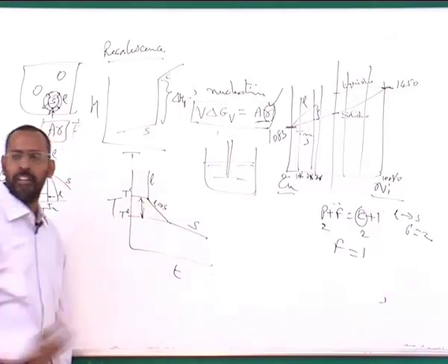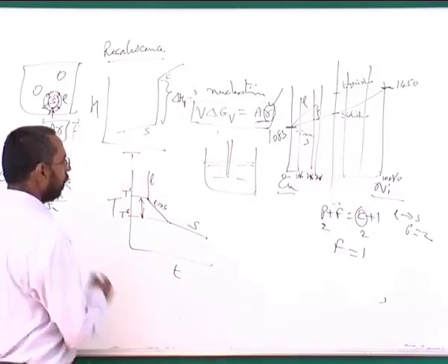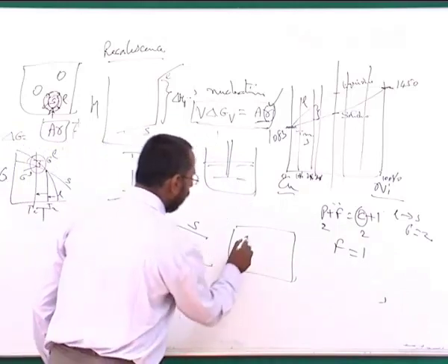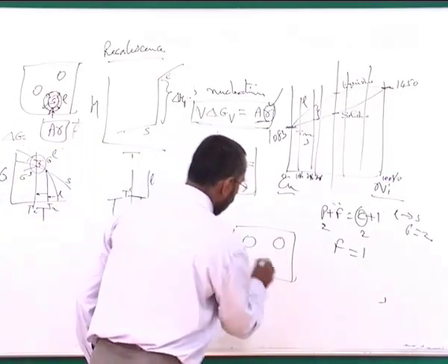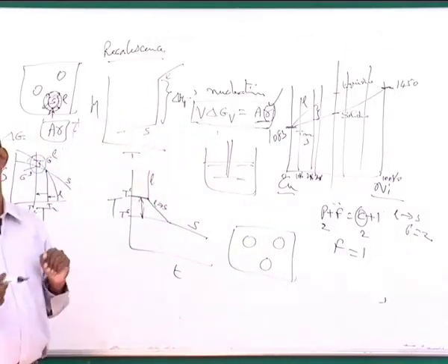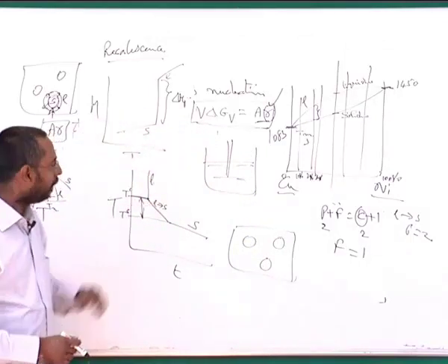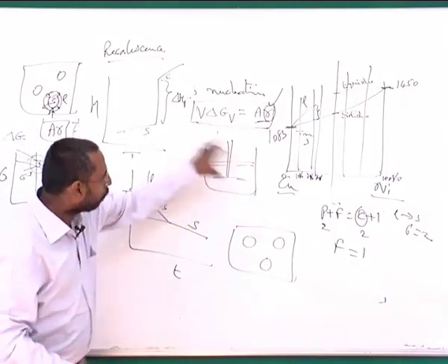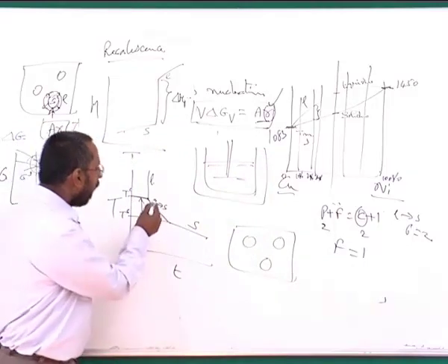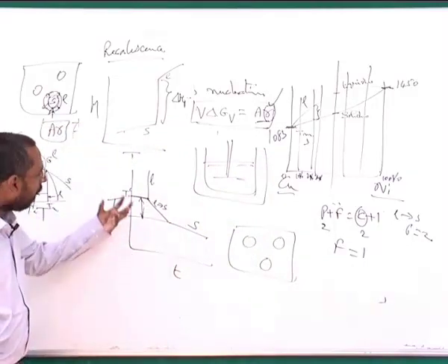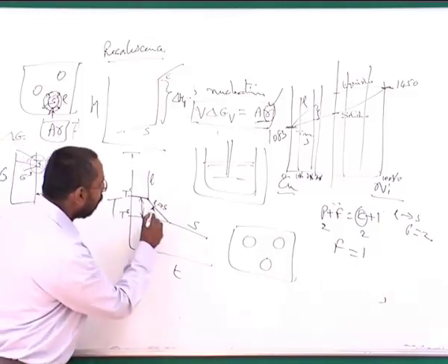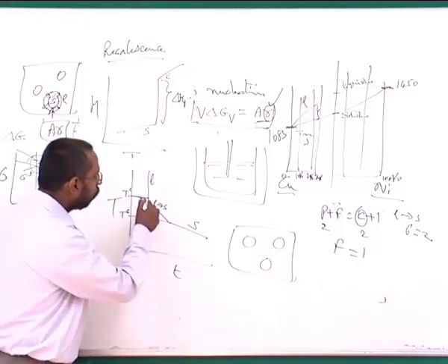Why this slope change happens is because the moment you have a liquid in which, at a particular temperature, the solid has nucleated at some places, the moment solid nucleates, heat is evolved. So the cooling medium, whatever mold you are using, has to extract that heat also. Because of that excess heat, the cooling rate suddenly comes down. So this slope is nothing but the cooling rate, and you will see that the cooling rate comes down.